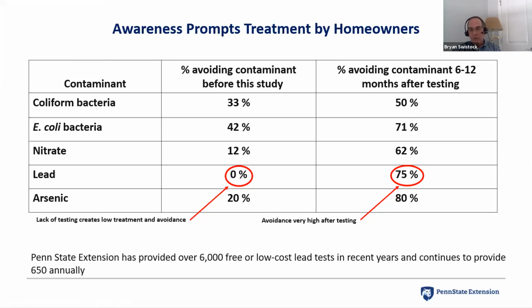But by the time we told them about it, 75% had taken action. They were using bottled water. They were flushing the water system. They were installing corrosion control or reverse osmosis or carbon filters. They were doing something. So it indicates there's a very strong interest, of course, in drinking safe water. That's a given. But that awareness hurdle has to be overcome mainly through the testing aspect first, and then we can start to match up the proper treatment.